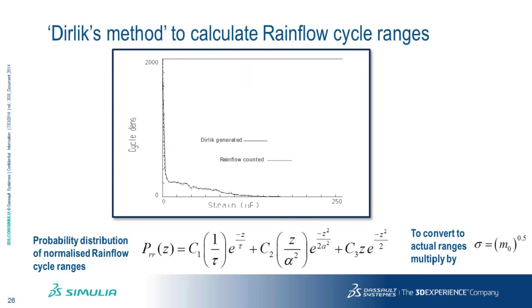This is actually a report that I did about 20 years ago for the wind energy industry, and it's looking at the magnitude of cycles, strain ranges, on the horizontal axis, and the numbers of cycles on the vertical axis. So this is like a cycle histogram. I've compared the histogram that you would get if you rainflow counted the time history of strain with the one you get from the PSD, and you can see they are virtually identical. And obviously, if the distribution of rainflow cycles is virtually identical, then the calculation of fatigue life will be virtually identical as well.